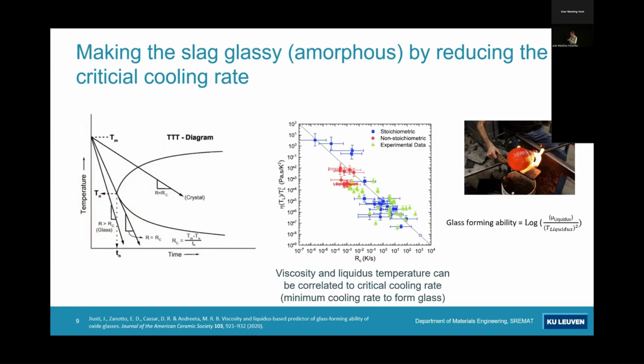And basically you can imagine it a bit as glass making. A good glass is something that has a low liquidus temperature and a high viscosity, so a very viscous mix and a very low melting temperature. That's ideal to form a glass. Of course, with slags, going that viscous is not possible. You will not get the slag out of the slag pot, but this is an ideal scenario. So you can use a formula that was devised in that paper to calculate glass forming ability.